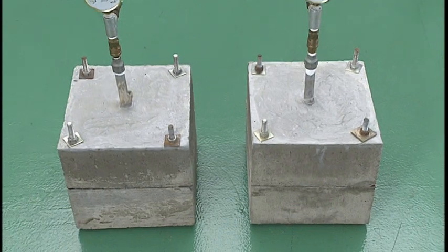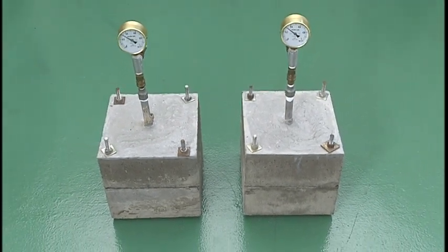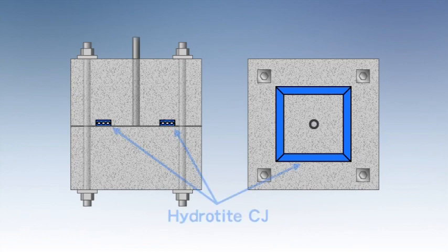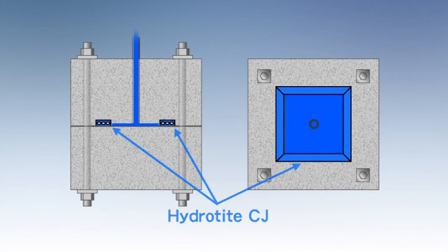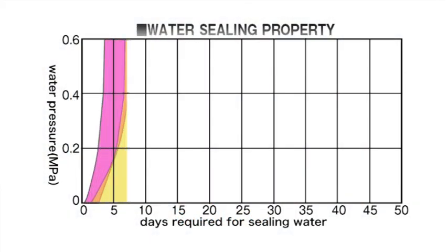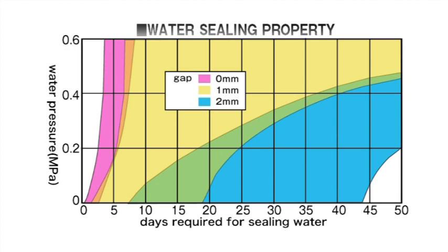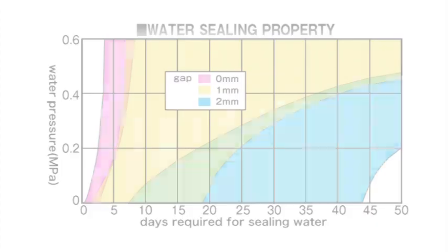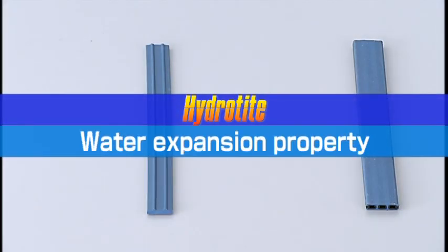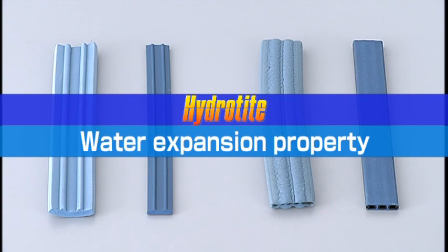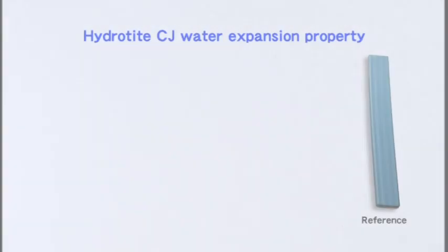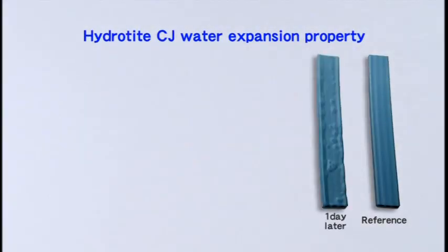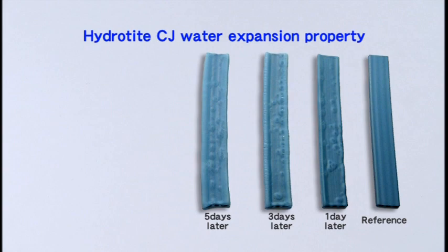We measured the water sealing characteristics using an actual concrete test piece. Water is poured in after attaching the test piece to the concrete. The graph indicates the number of days required to seal water while raising water pressure in gradations of 0.1 megapascals following pouring. The water expansion performance of Hydrotite is designed according to various uses and displays effective water sealing performance. This is Hydrotite CJ's water expansion property.